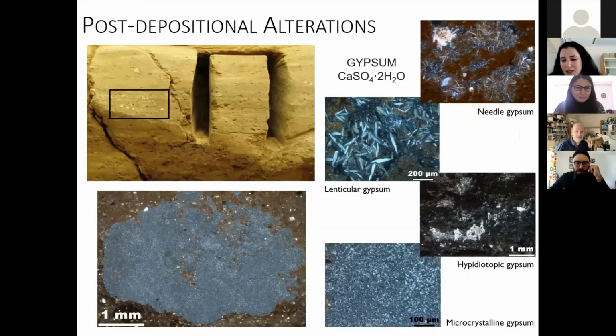Precipitation of gypsum salts is really common in arid and semi-arid climates where soil moisture easily evaporates and salts from solution are deposited. I have observed this phenomenon in all the central Anatolian sites I have worked at, with white nodules up to several millimeters in size, often becoming visible macroscopically in the field. So, as you can see in the first photo here.